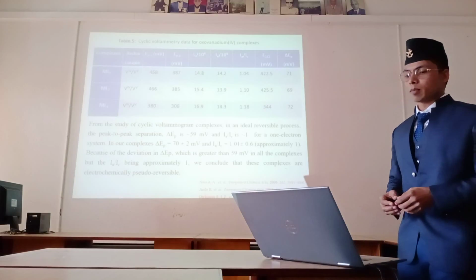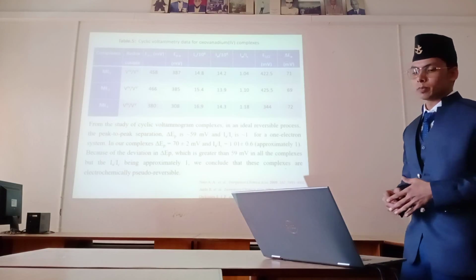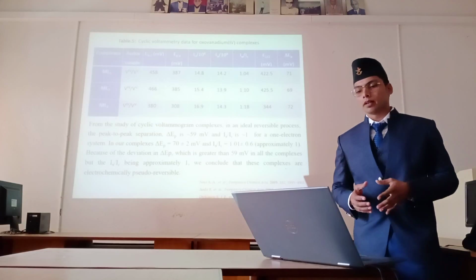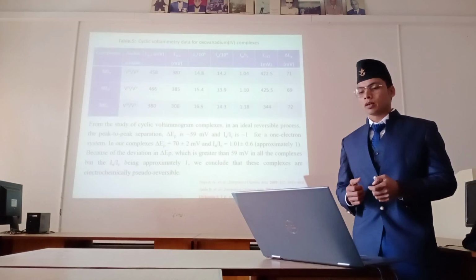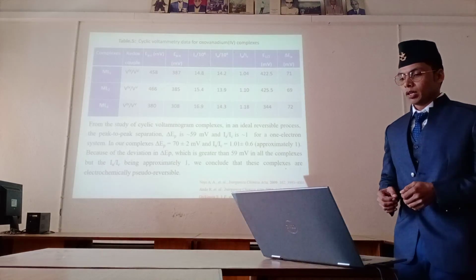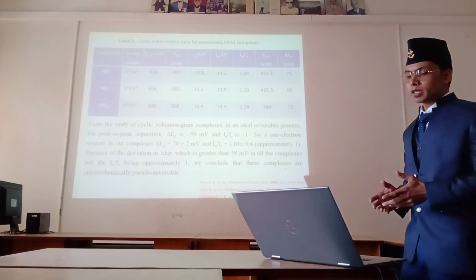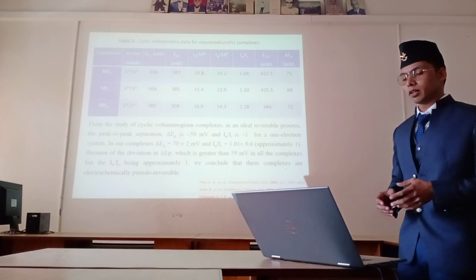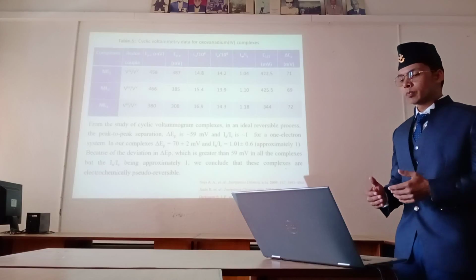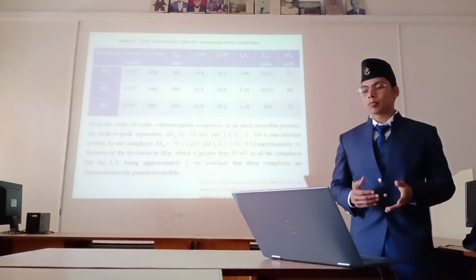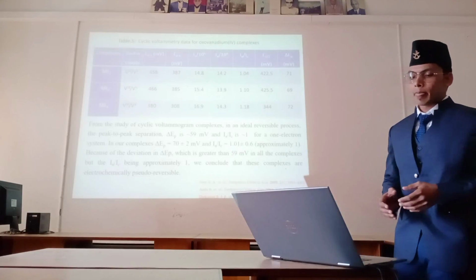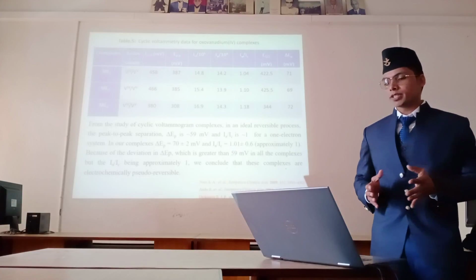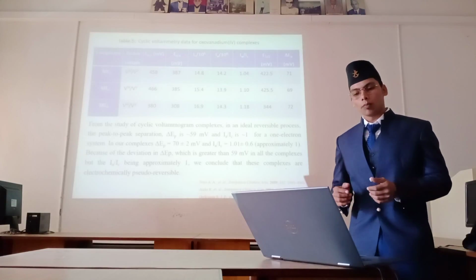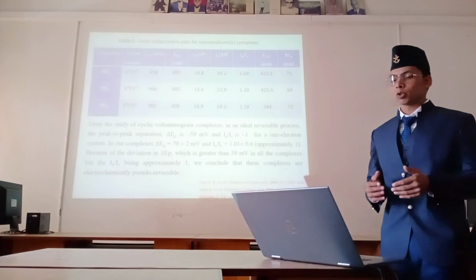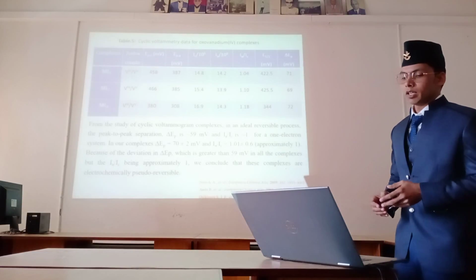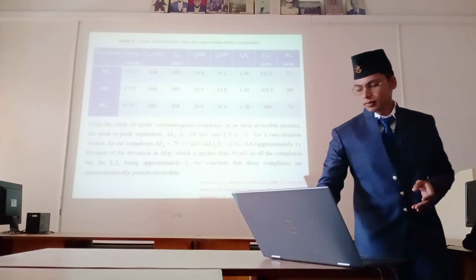From the study of the cyclic voltammogram of the complex in an ideal reversible process, the peak to peak separation is nearly equal to 59 millivolt and the peak current ratio is nearly equal to 1 for a 1 electron system. In our complexes, the peak to peak separation is equal to 70 plus minus 2 millivolt and the peak current ratio is equal to 1.01 plus minus 0.8, approximately 1, because of the deviation in the peak separation, which is greater than 59 millivolt in all complexes. For the peak current ratio being approximately 1, we conclude that these complexes are electrochemically pseudo-reversible in nature.